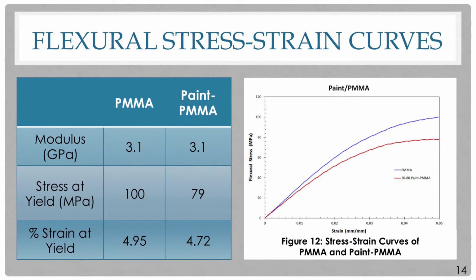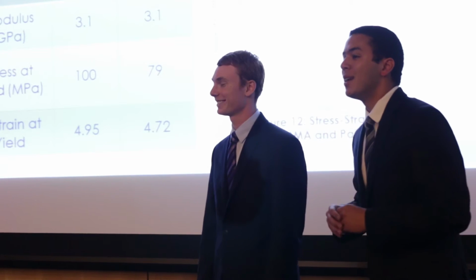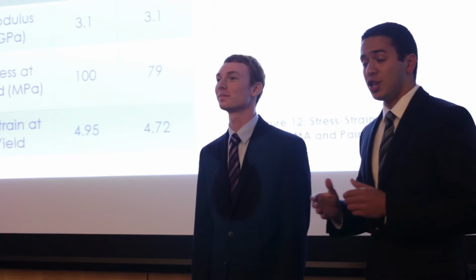If we take a look at figure 12, one representative specimen was selected to best represent our data. At the end of the curve, the stress at yield can be found, which is an indicator of the flexural strength of the material. The red curve, which represents a 20-80 paint PMMA, is actually below the blue curve, which is a PMMA, and thus the flexural strength of the paint PMMA polymer blend is less than that of the PMMA.